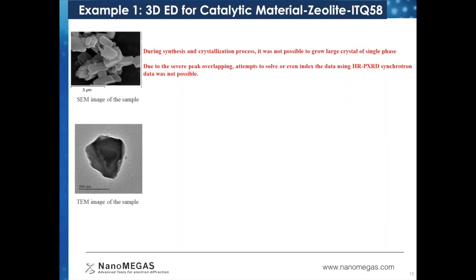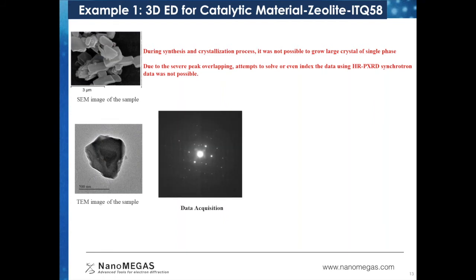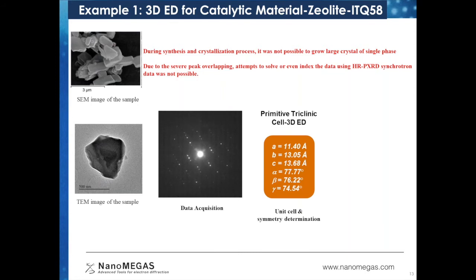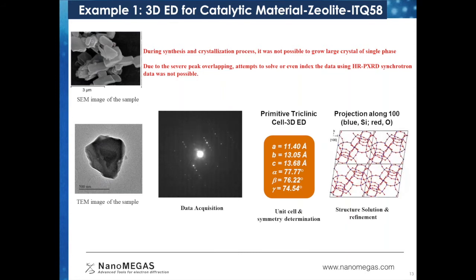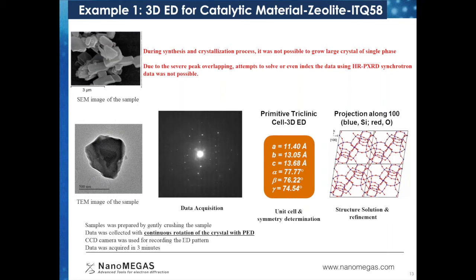The sample was prepared by simply crushing the material, and data was collected by continuous rotation of a small crystal in combination with beam precession. From the obtained data, we found the unit cell and the symmetry, and ultimately solved the structure. And we also did a Rietveld refinement of the obtained structure from electron diffraction data. The data collection took close to 3 minutes, to reduce beam damage, and the work was published in JACS in 2016.